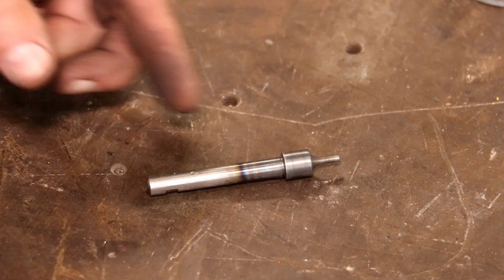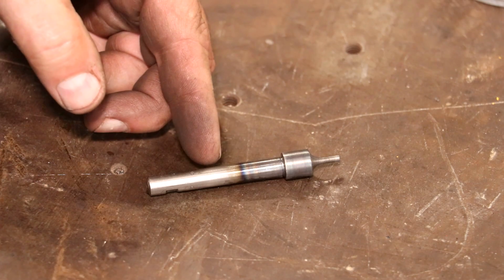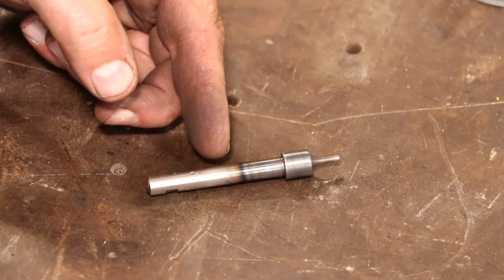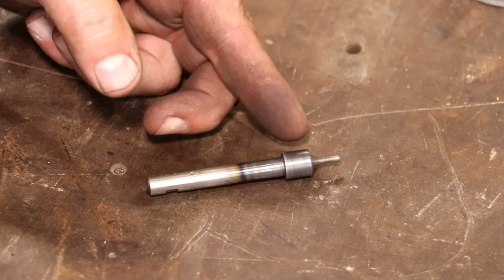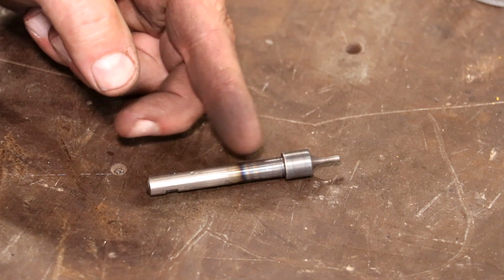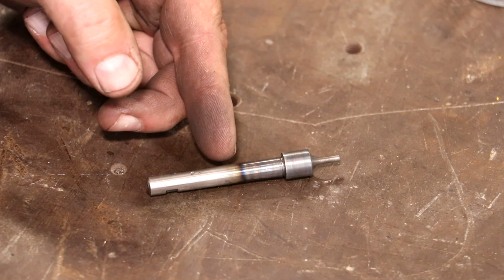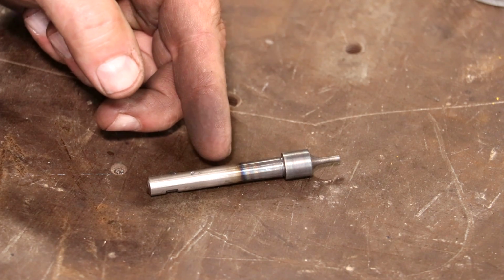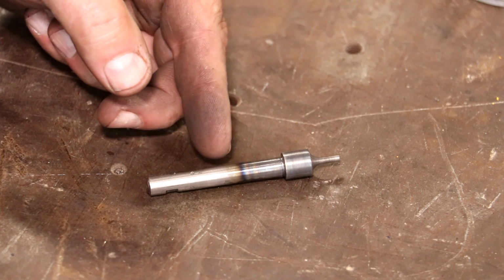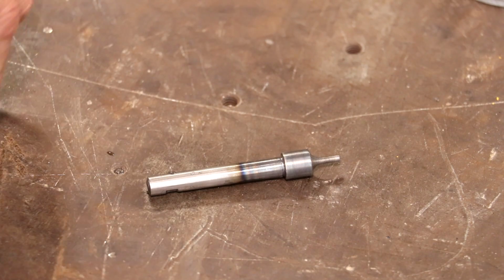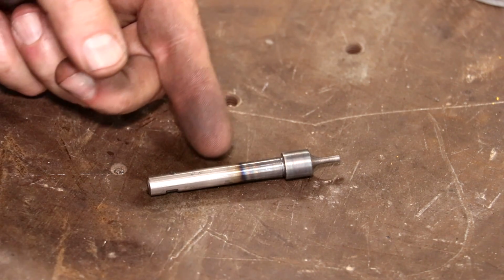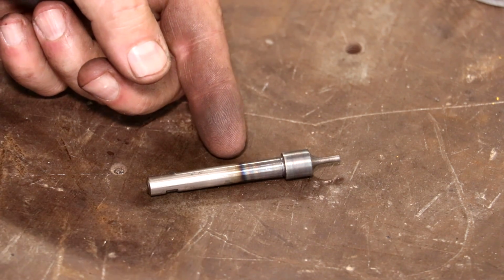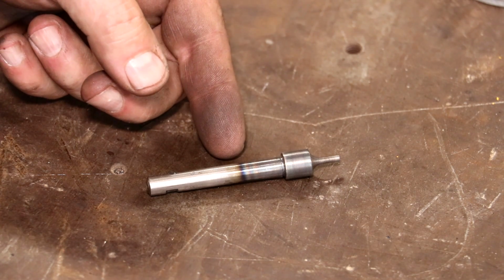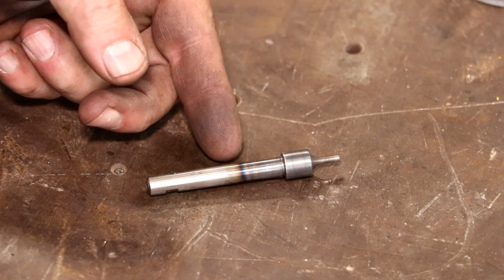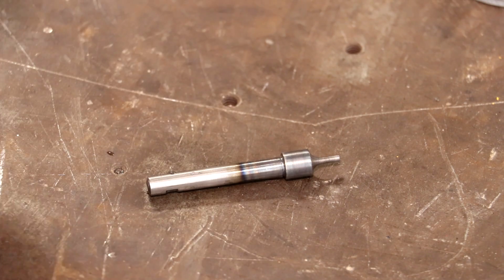You can kind of see here a gradient in the color of this metal. It was semi-polished, so this is an indication of hardness. And this is actually after you temper it, but because it didn't get up to full temperature down on this end, that straw and blue colors kind of give you an idea of how hard it is. Really doesn't mean anything right now, but that is an old blacksmith's way of looking at hardness rather than actually testing it with a hardness tester. You could just look at the colors in there and you can see it pretty evident there. I wanted to show you that. Again, the tip is too hard right now.